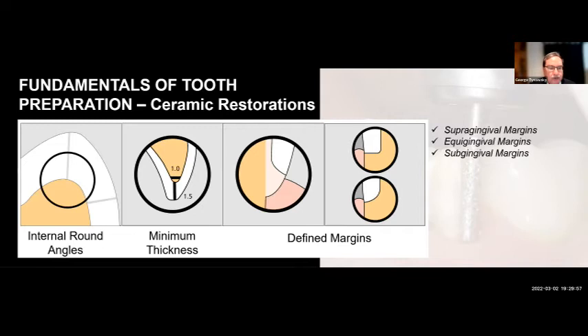The other factor is we want to provide enough thickness to the material, depending on the material we're using. And then typically we define them with a defined margin, so a deep chamfer or a shoulder preparation with very clearly defined margins, so the instrumentation can clearly fabricate those restorations. The one thing I want to note is that this is a really important criterion, especially for lithium disilicates and for the 4Y and the 5Y.